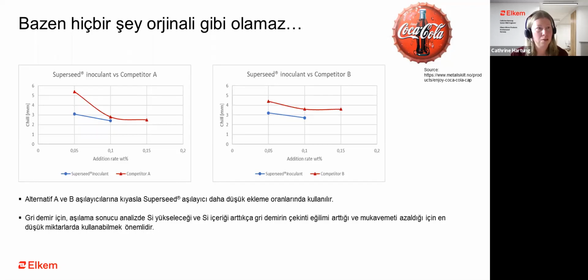But remember, at this time, the dominating inoculation method was also ladle inoculation. Today, we are stream inoculating. But still, it is designed to give maximum chill reduction with lowest possible addition and thus minimum additional silicon. So you're retaining the maximum amount of strength you can get from the chemistry of the gray iron, because in gray iron, it is predominantly the carbon equivalent that will determine what kind of strength the iron has. And you use silicon to offset the formation of carbides in the solidification, but at the expense of a higher risk for shrinkage.